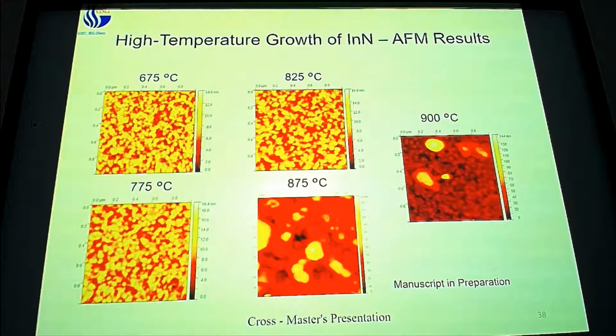We took this and we did AFM measurements of the sample. So we put it underneath an atomic force microscope, and we actually measured the surface of the sample. That measurement showed us what this indium nitride looked like. And you guys remember the gallium nitride from earlier? Nice and flat with those beautiful layers. This does not look like that. So as you can see here, at the lower temperatures, 675 and 775, we have a very granular mess. It is indium nitride.